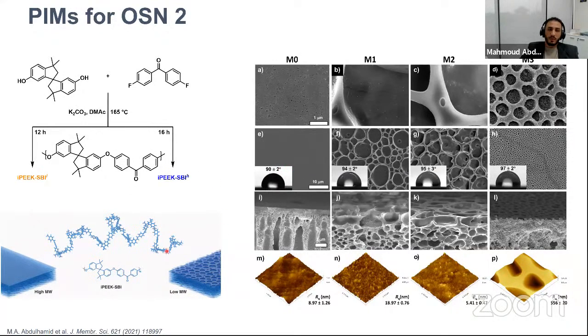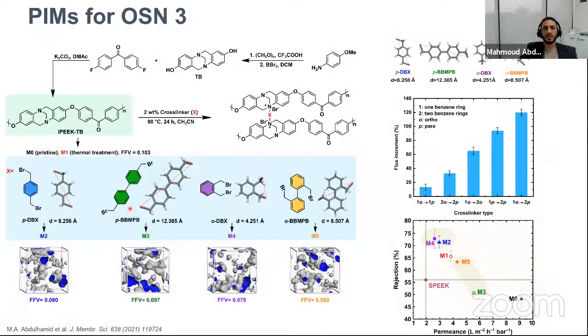When we talk about organic solvent nanofiltration, it's important to consider that the membranes we are using are stable in organic solvents and acids. These are stable in a specific type of organic solvents, but some polar aprotic solvents like NMP can still dissolve them easily. So we wanted to enhance the stability of these materials. Then we thought about cross-linking. Cross-linking is a well-known strategy to enhance membrane stability, but it has some requirements.